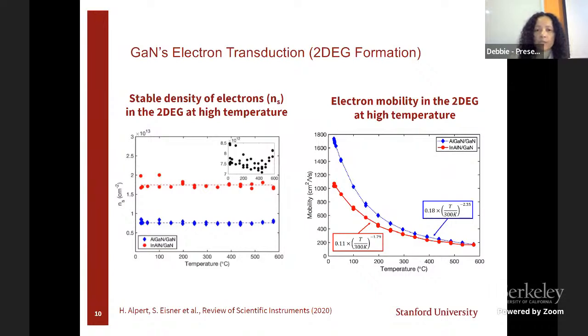And so we're often wondering, what is the nature of this 2DEG, especially at high temperatures? This is some work on our sheet density, N sub S. The blue dots are for AlGaN/GaN, stable from room temperature up to 600 C, and this is collected in air. And then a different doped variant, indium aluminum nitride on gallium nitride. So we can, again, change that top layer in the heterostructure. It has a slightly higher, but also constant, sheet density as we move from room temperature up to 600 C. And this data in particular is collected in air.